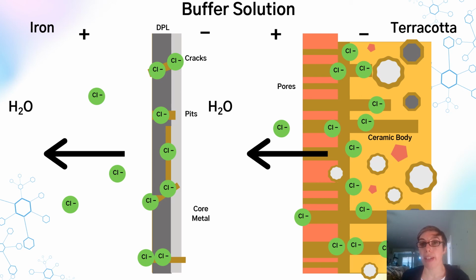Another factor that we have to take into consideration is that desalination is not risk-free, and by reintroducing or keeping wet artifacts in water baths for long periods of time, even highly purified ones, we can still promote renewed degradation of the artifacts, especially materials like iron, which are super reactive and will pretty much continue to corrode as long as they have access to water, oxygen, and electrolytes into perpetuity. This is especially true as we prefer to remove any concretion, any overburden, or more extraneous layers of corrosion material from the surface of the artifact, both to make the artifact more legible, but also to allow greater access for diffusion, and also to remove any chlorides that have accumulated inside those most superfluous layers. However, by doing this, we've also exposed more of the artifact surface, including any core metal that is still there, which basically opens it up for further corrosion processes.